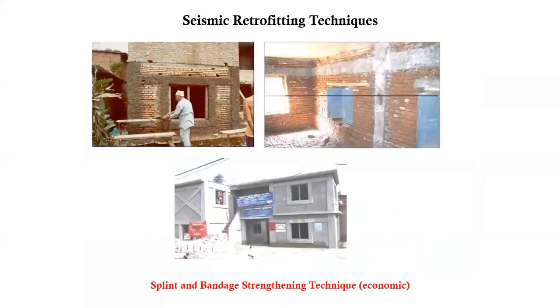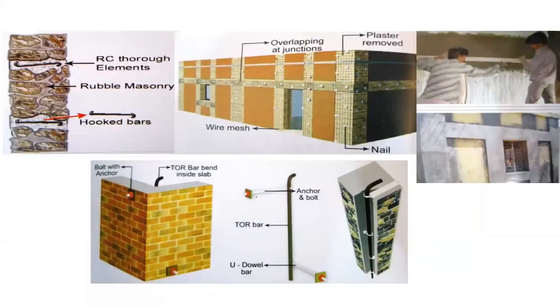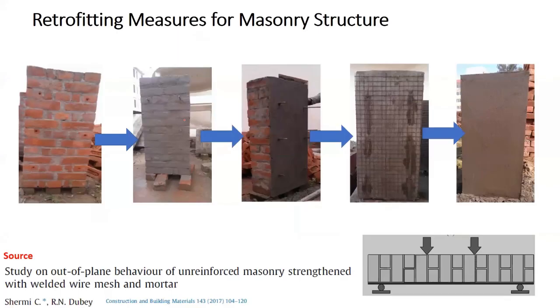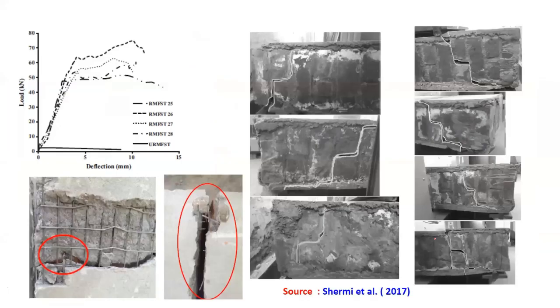This is a typical example that has been done. One of my fellow researchers did this research. For example, this is the masonry wall, and they provided the anchor and base mortar to keep the level equal. They used welded wire mesh and again plastering, and then tested it under bending. It is an out-of-plane bending test of masonry walls.